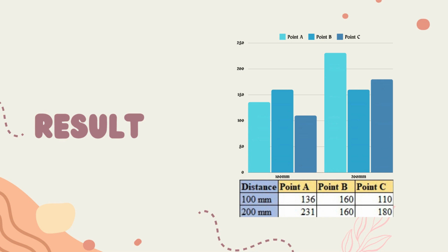The distance for 100 millimeter for three locations: point A got 136, point B got 160, and point C got 110. For 200 millimeter, the highest reading for point A was 231. Point B, same as 100 millimeter, got 160, and point C got a higher reading, which is 180.